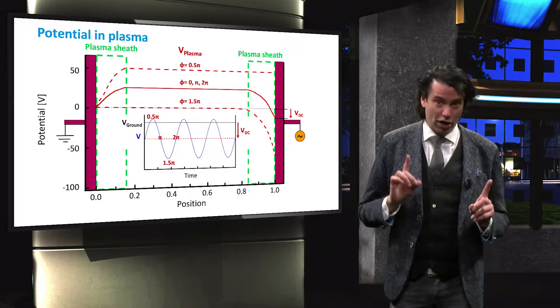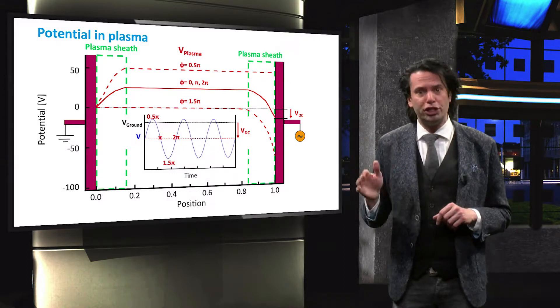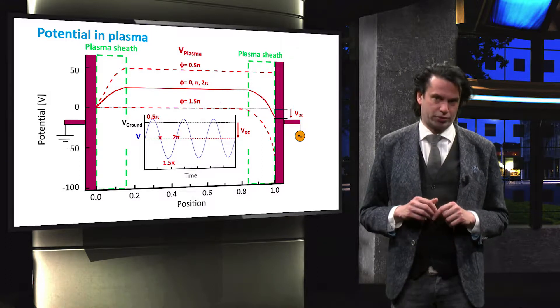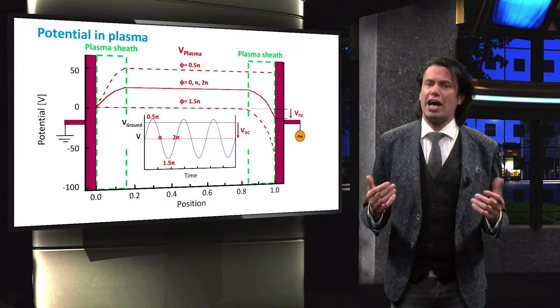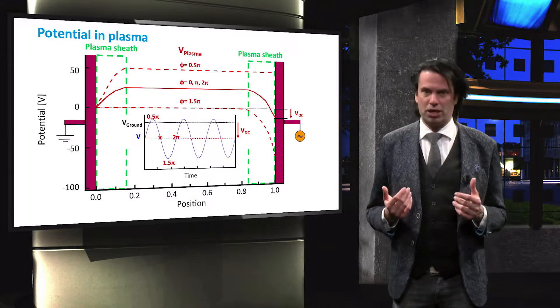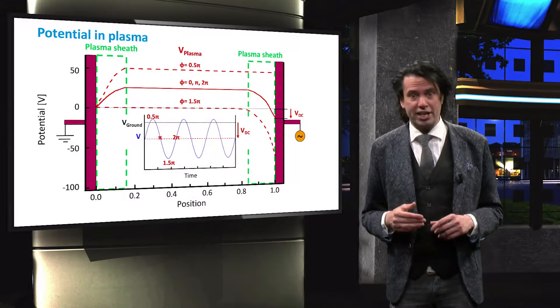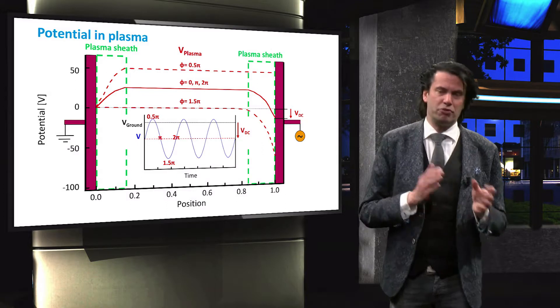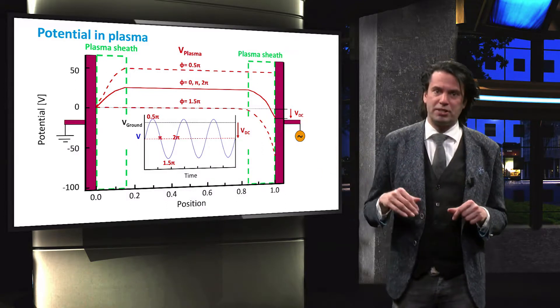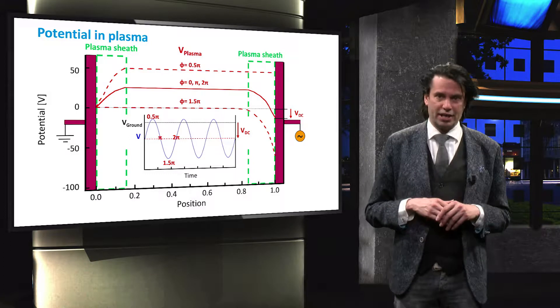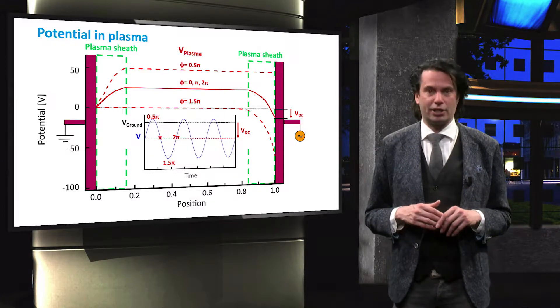There is now, however, a large voltage drop across the sheath region of the grounded electrode. The grounded electrode will therefore experience increased ion bombardment. The substrate, which is located at the grounded electrode, will therefore experience a cycle of ion bombardments and electron bombardments, depending on the applied external voltage.